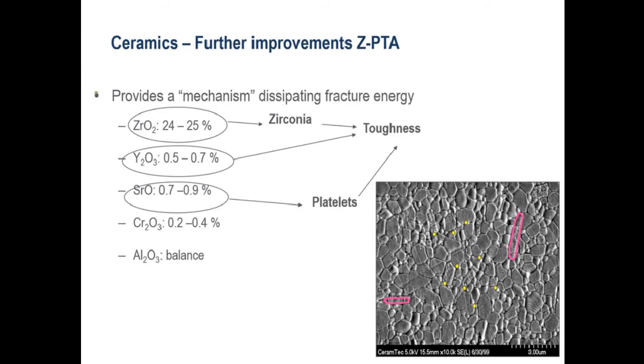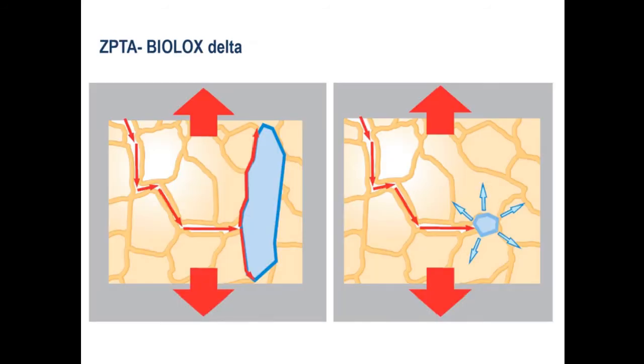Further improvements in ceramic materials utilize the good toughness of zirconia and the good hardness of alumina ceramics. And you end up with a composite of alumina and zirconia oxides where the zirconia acts as crack dissipation when a crack is initiated within the alumina matrix. And this is an illustration of a zirconia toughened alumina structure showing how the crack is dissipated by the platelet or the zirconia particle when it's initiated within the alumina ceramic.